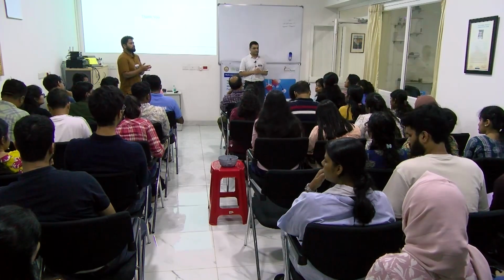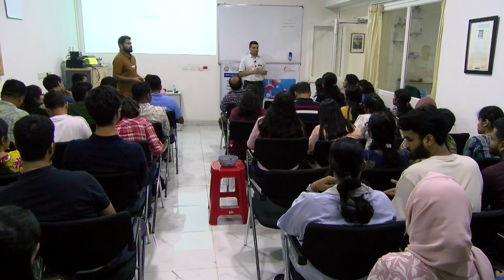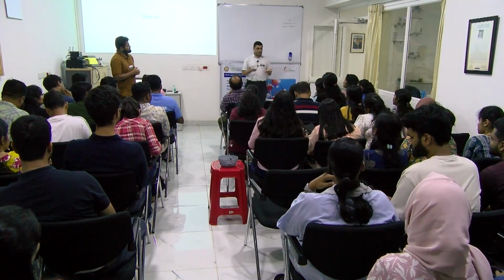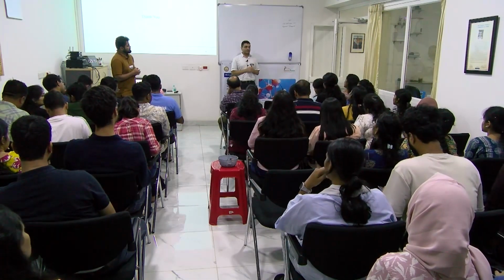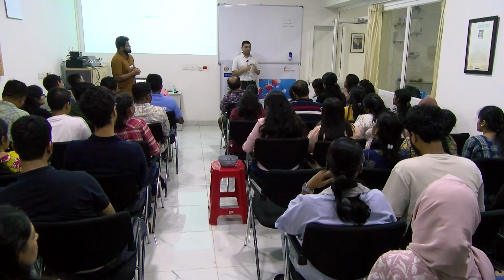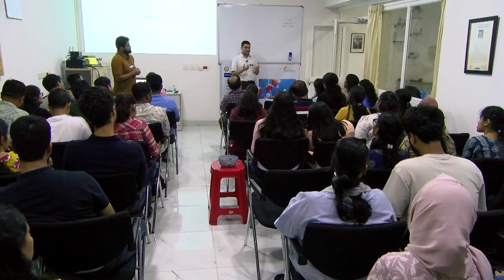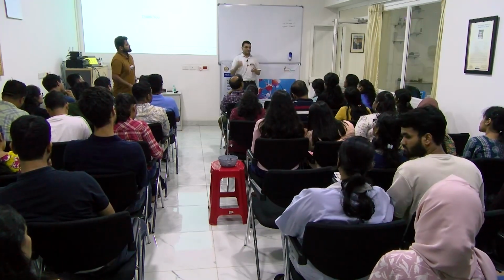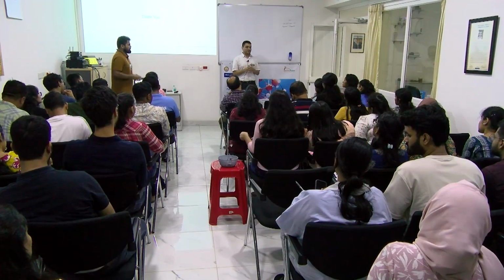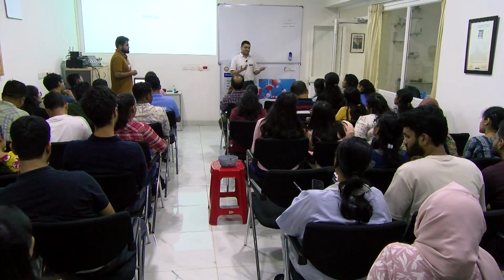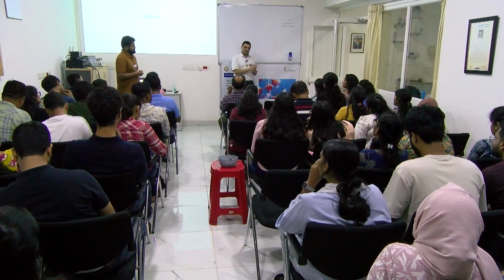Okay, and one more question. Though MOF is really exciting, it's been quite a while now that COF is taking over all the attention. So, what's your take on that? So COFs are exciting, of course. They're way more porous than MOFs are. The limitation with COFs is that you have to build big organic molecules to ensure that you get more porosity and functionality. Those can be slightly more expensive. Whereas with MOFs, one part of your building units can be really cheap. I showed zirconium, that is not cheap, but you can start working on things like iron and things like that. So the overall cost aspect can be slightly in favor of MOFs.